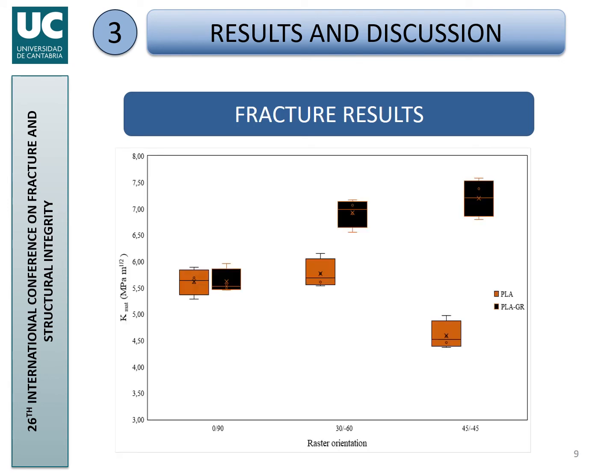Concerning the fracture results, here you may see what we obtain, and it is pretty interesting because the addition of graphene on the fracture properties and its effect strongly depends on the raster orientation. Particularly for raster orientation 0/90, there is very little effect or negligible effect.